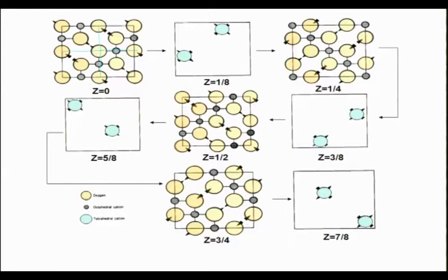So you put 2 tetrahedral atoms, which is the A atom. So these are the octahedral atoms. Okay. These are FCC unit cells. So when you go to Z equal to 1/8, you go to the plane in which tetrahedral interstices are there. So tetrahedral interstices, you fill only 2 of them, you don't fill all of them, because you cannot fill all of them, you have only 1/8 occupancy. So you have filled 2 of these tetrahedral sites in this fashion.